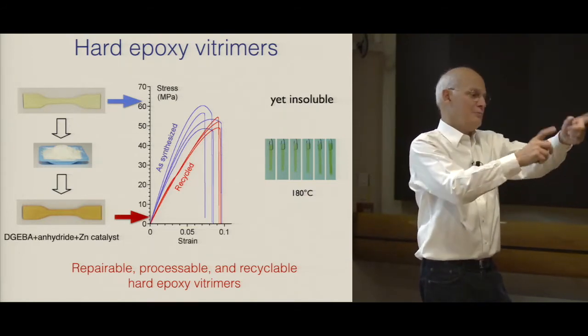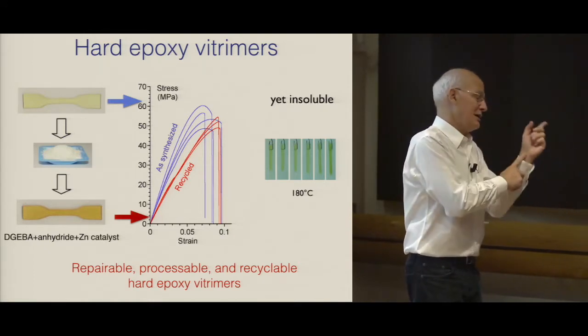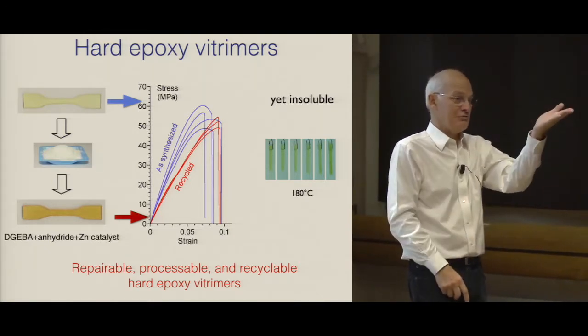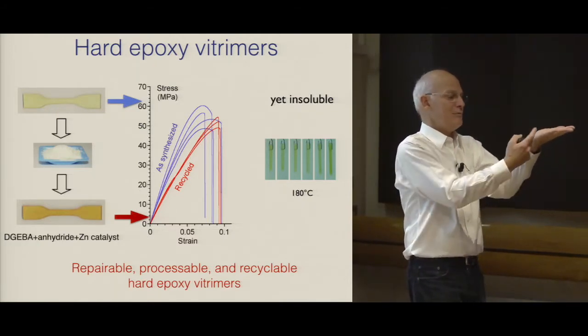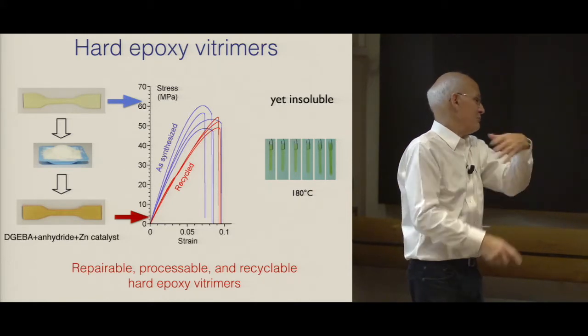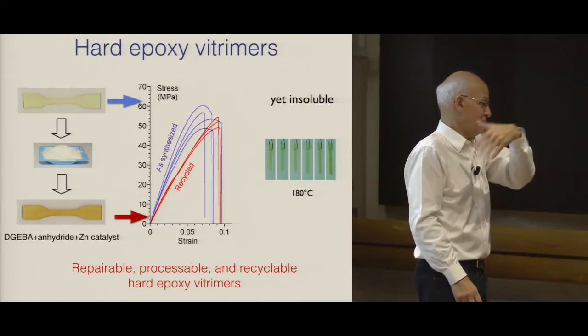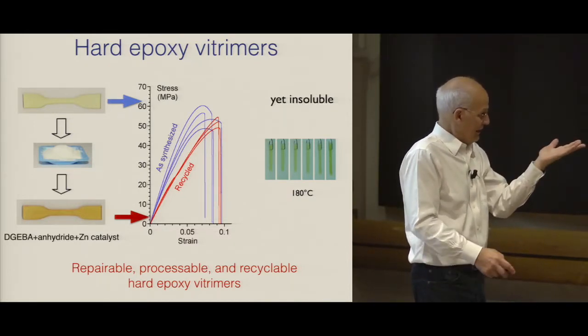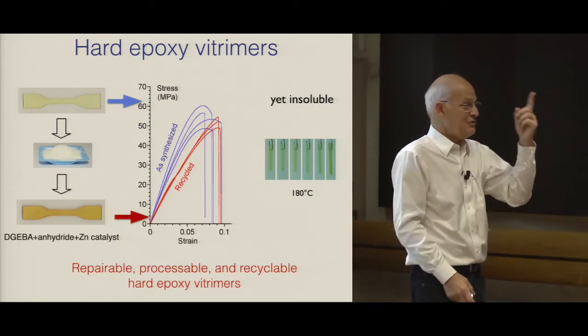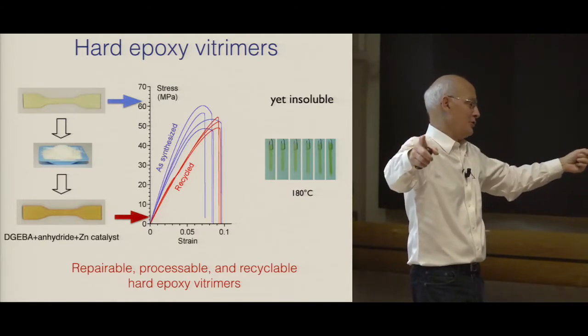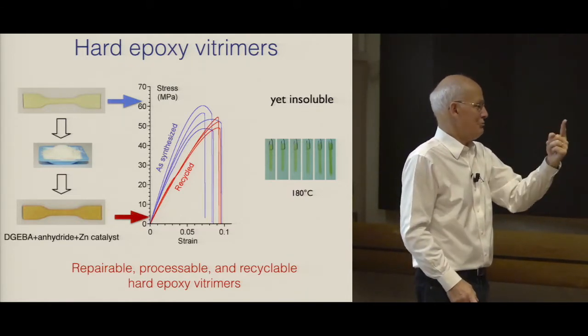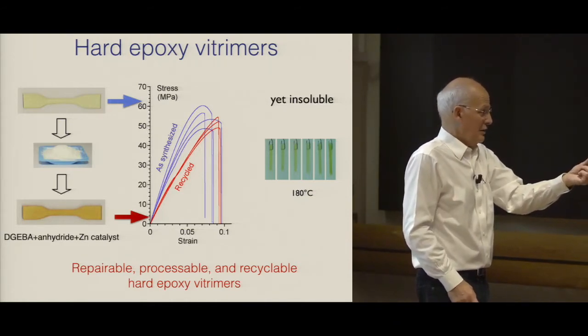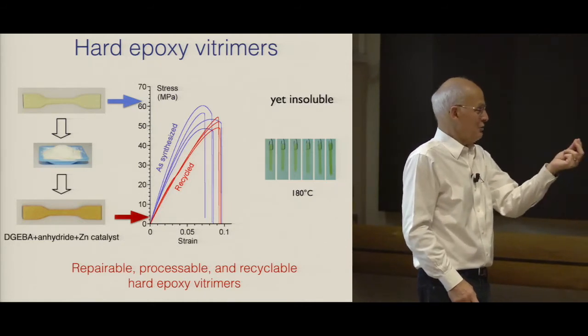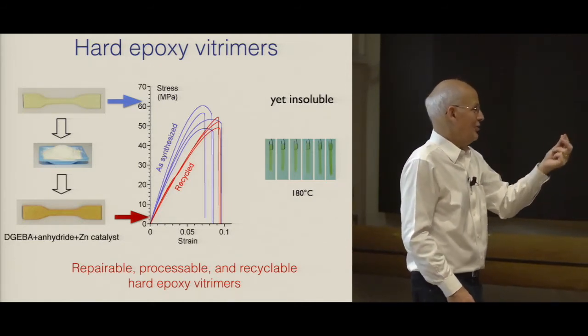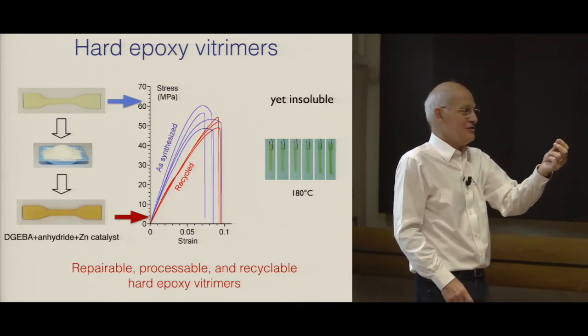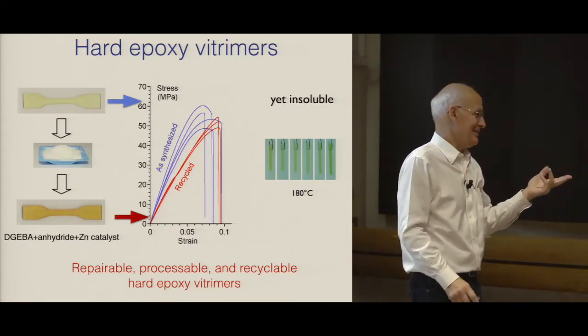If I want to extrude my polymer, and I have secondary reactions, which means I heat this polymer to 200 degrees and then I have secondary reactions which make permanent crosslinks. So instead, I don't know, I use transesterification and I make ethers rather than esters. Then I will have a permanent crosslink, and it's sufficient to have one crosslink per chain. So if the chain has 1,000 monomers, 1 in 1,000 of secondary reaction will block the extruder. And when people look at organic chemistry of small molecules, if they have a yield of 80% or 70%, they say, oh, it's nice, or maybe not so nice, but it's okay.